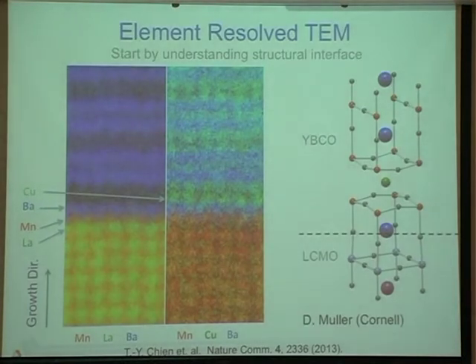So this led us to doing some very detailed structural studies of the interface. First, we did cross-sectional TEM, which allows us to look at where the atoms are. This was done with Dave Muller's group. And this allows us to really look at the interface chemical structure in this material. What you can see is there's a very sharp divide. You have this manganese layer, the manganese are the red ones. Then I have a barium oxide layer, and then I go into this copper-oxygen double plane. This is a schematic picture here on the side. So we know really what this chemical structure looks like. It's very sharp, and this is one of the nice reasons for this system, that you can create these heterostructures and then study the details.